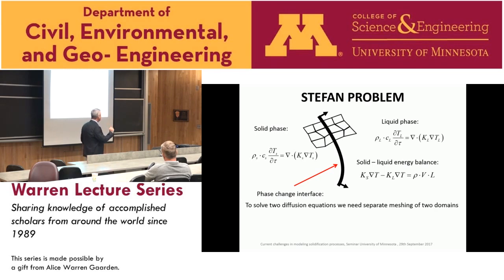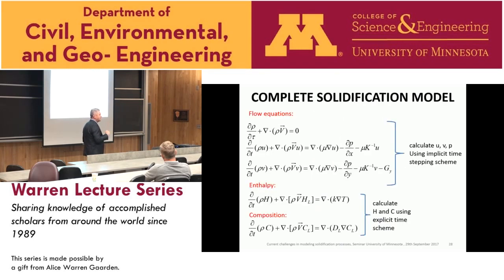We can control it through the value of the constant K0, and we can impose less or more permeability. This is a rough approximation, and when you are in the mushy region, this term becomes dominant, and they cancel almost all other terms, and then you have it competing with the Darcy term and the pressure gradient. And this is the base of how you calculate the U and V.